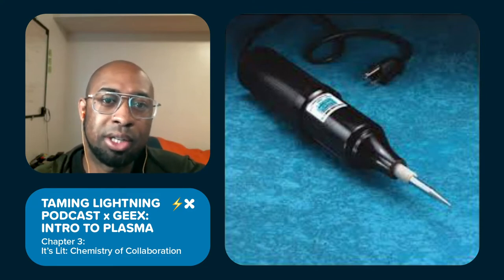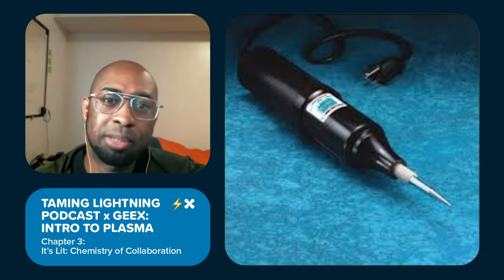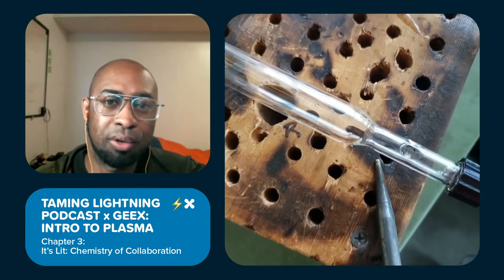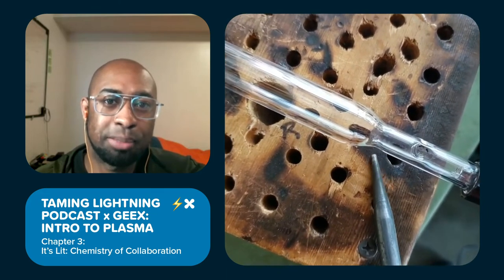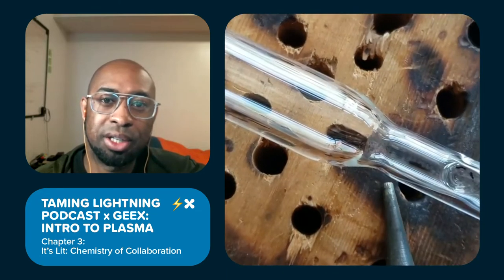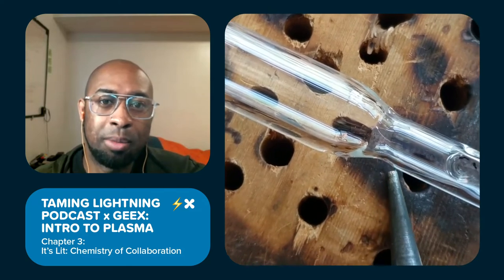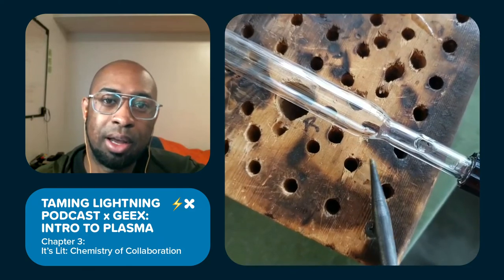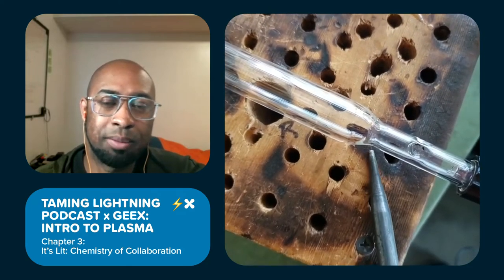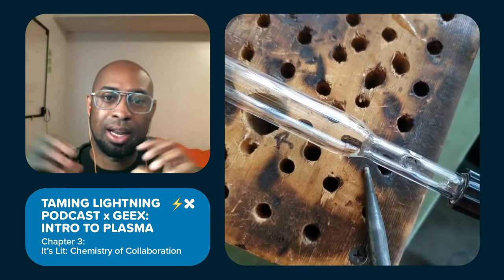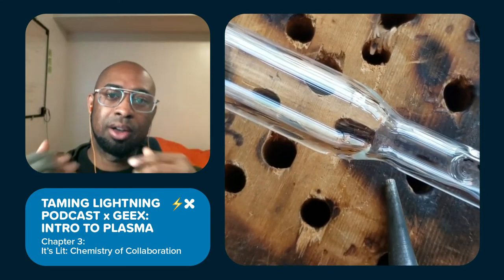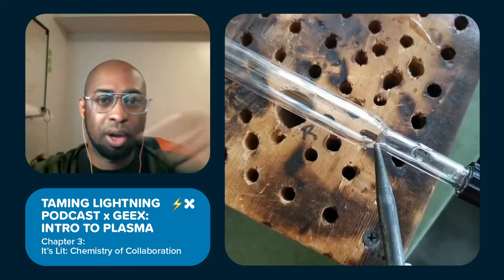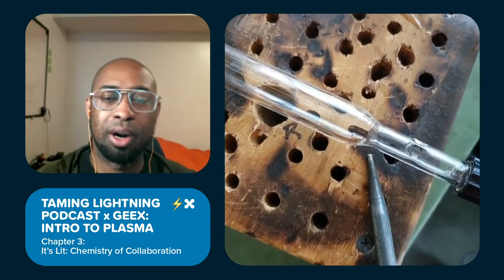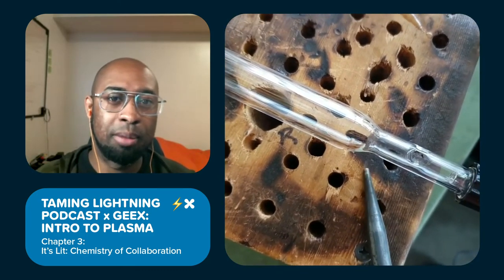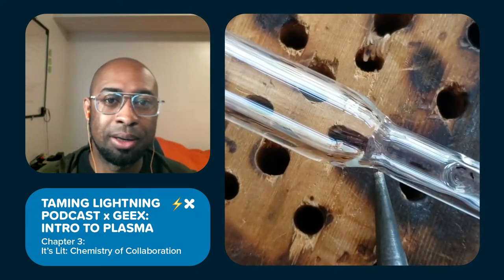All right, so next you'll be taking the tip. You'll put the spark coil on the lowest possible setting and point the tip towards the electrode wire, keeping the spark as small as possible and at a short distance from the glass. You'll be checking all connected areas and manipulated areas of your glass. Any area that has any connections has potential for leaks, and areas that have been stretched from poking holes through can create areas where you may also search for possible thin or weak spots.